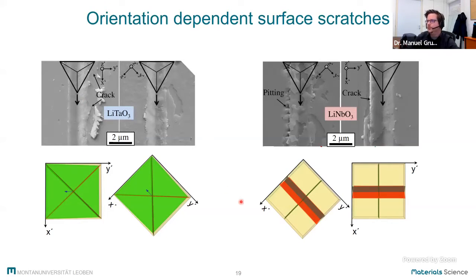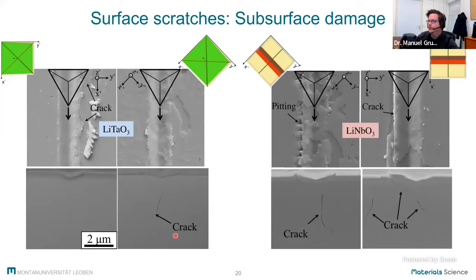on our specimens. And when we looked at how the subsurface damage looked, we could see that the worst case scenario is scratches parallel to the cleavage planes in the relatively soft lithium niobate. So we get a very huge network of cracks underneath the surface. And for the hard lithium tantalate in certain directions, there's even no subsurface damage visible, only small cracks on the surface.